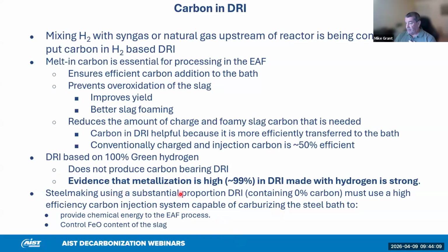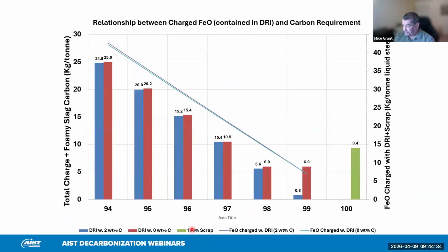But with a higher metallized zero carbon DRI, we need to have a carbon injection system that is well controlled and high efficiency. So 50% efficient, as in the traditional carbon injection systems, is not good enough. We need to go higher. And the amount of carbon, of course, depends on the metallization of the DRI that you're charging.